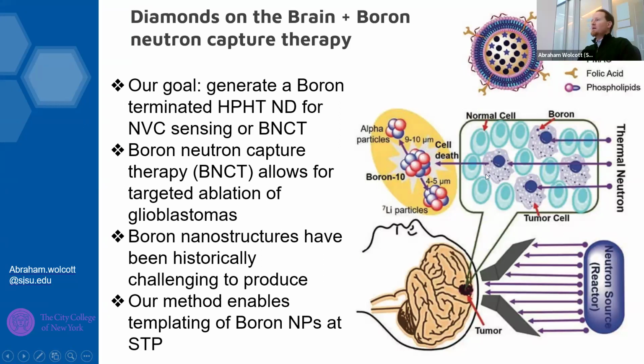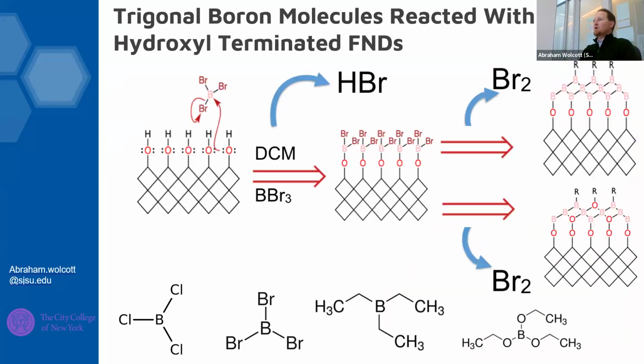Those alpha particles then destroy and heat up localized cancer cells, and there is a high level of efficacy in this therapy for reducing the size of cancerous brain tissue. But boron nanostructures are typically made with borane gas and high power lasers. So many folks have stayed away from it for many years, but now there's been an increase in the synthesis techniques. So our method, which I'm about to show you, enables us to template this boron onto our nanodiamonds at standard temperatures and pressures. So we hope to be able to expand this going forward.